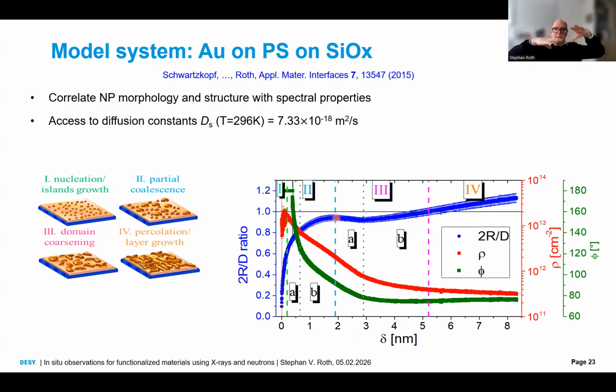At one point, the clusters which could move on the surface are too heavy, and they stay in their position, and they just attract and trap all the other atoms coming in. So basically the distance grows, and they grow in some kind of Vollmer-Weber growth. The big clusters eat up the small mobile clusters, and therefore we have this dip here because the distance increases by eating up small clusters, so to say. And when we continue with the deposition of gold, the clusters grow and touch each other. And when they touch each other, we have a percolated layer. So by simply analyzing the 2R/D ratio, we can tell you when this layer should become electrically conductive.